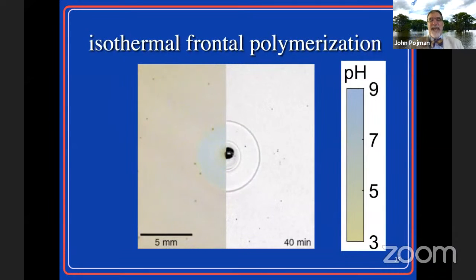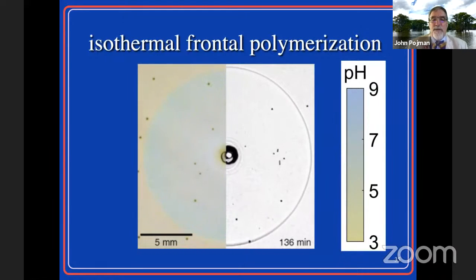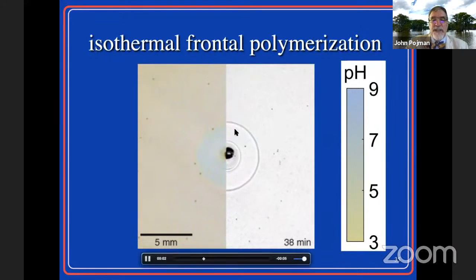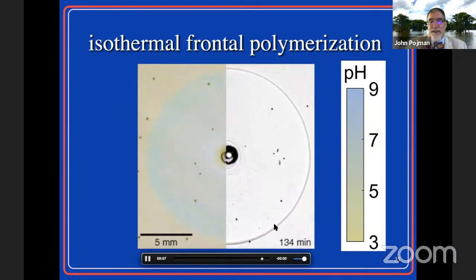It's also possible to get a propagating front. So this is a movie that is sped up. But what's happening, it's a split view. On the left is a pH indicator system. So we started out a system at low pH, add a little bit of base. The reaction causes the production of ammonia, which diffuses, causes fast reaction, and you get a reaction that propagates with a constant velocity. This is showing that simultaneously we're having a conversion of monomers into polymer. So this is an exciting process.